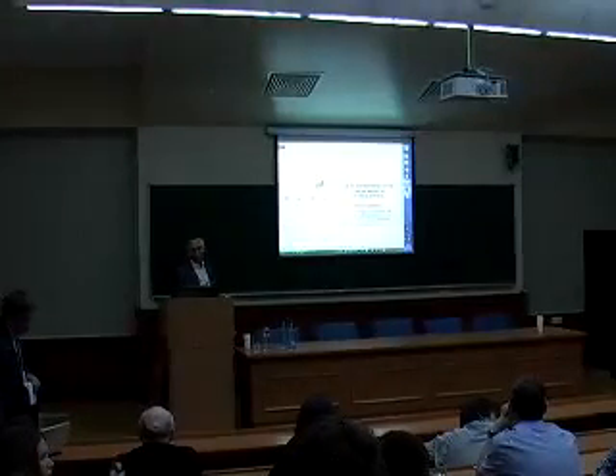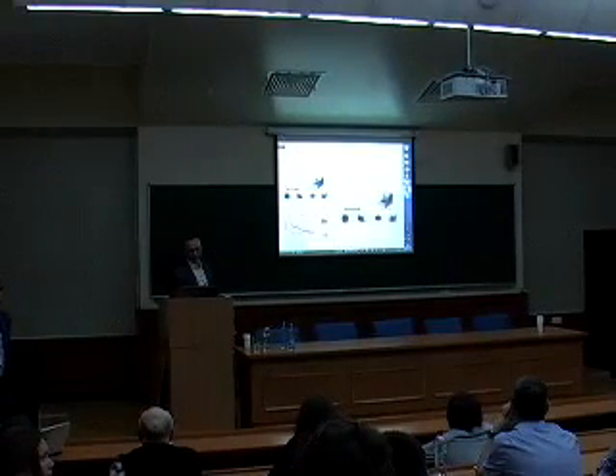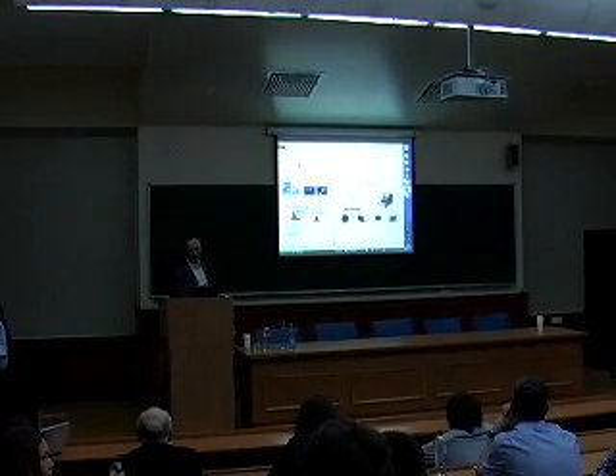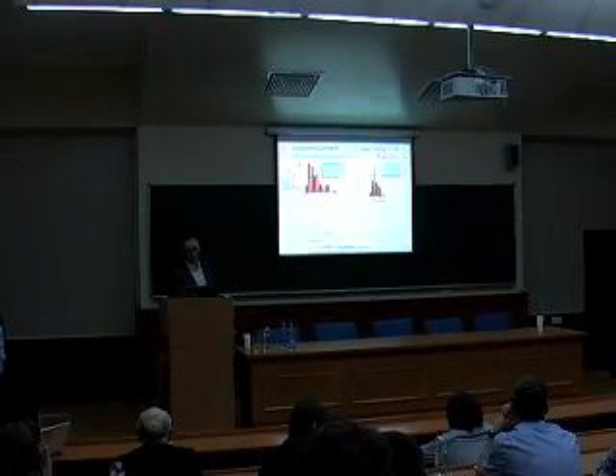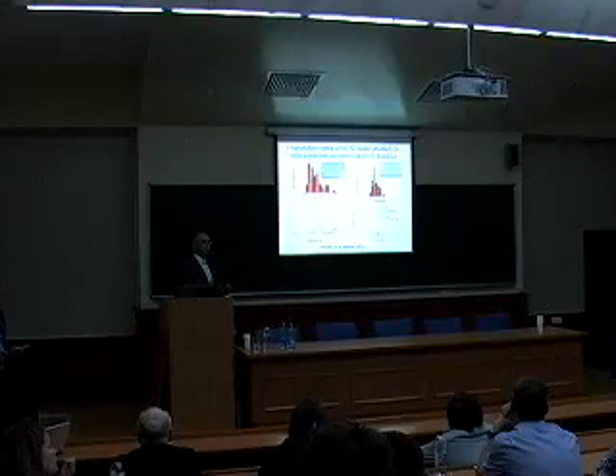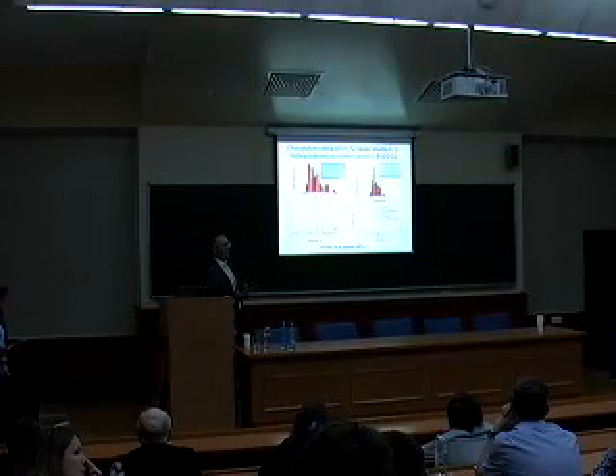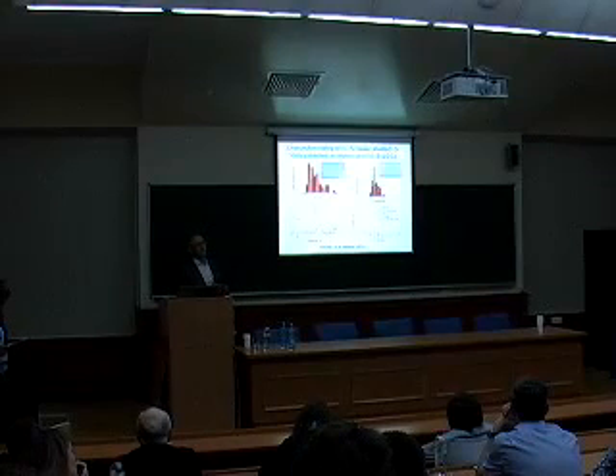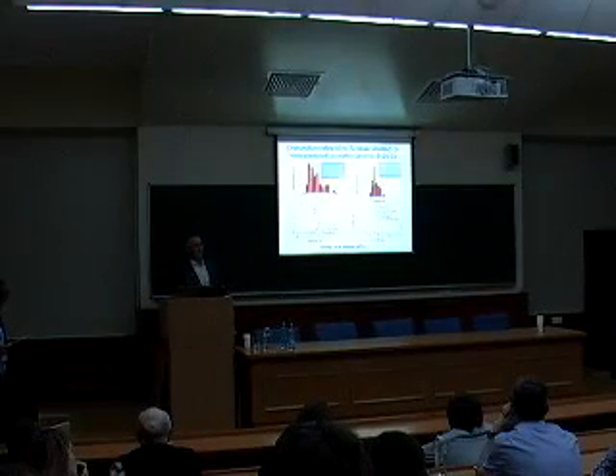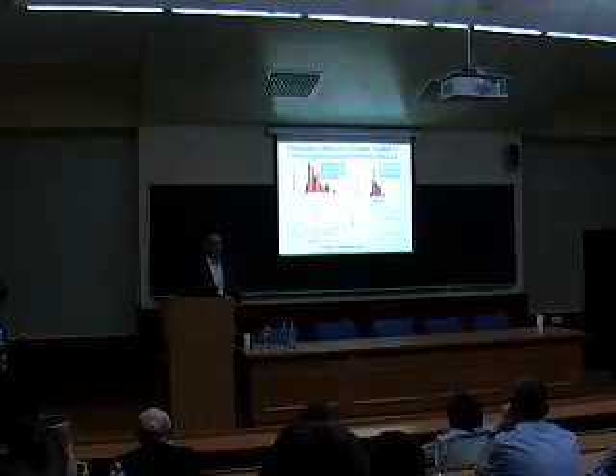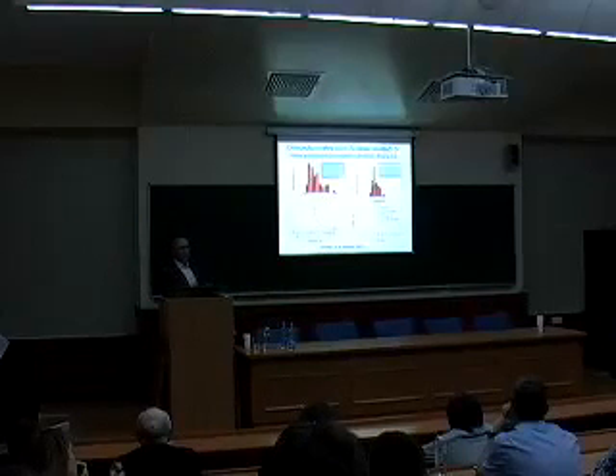I want to ask you, you showed us one slide about this change of size of silicon nanoparticles with time. Can you give an explanation for this? Why is the size of particles changing? This is the dissolution process, because silicon, like aluminum, is, by the way, a very reactive material in water. It oxidizes, and this thin oxide can be removed or dissolved by creating orthosilicic acid. And we exactly obtained this situation.